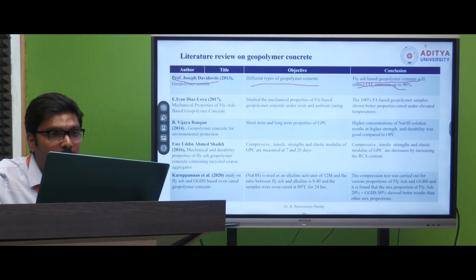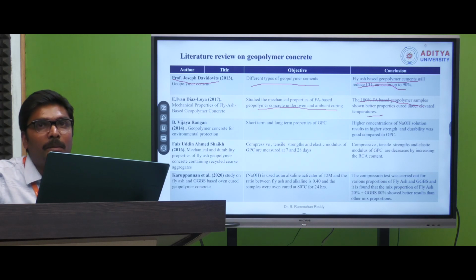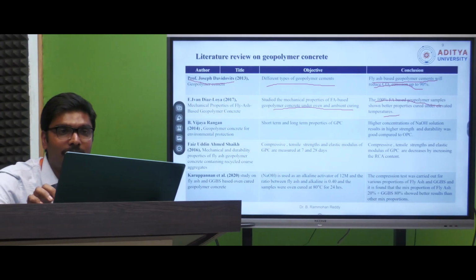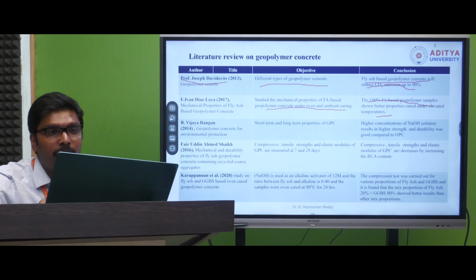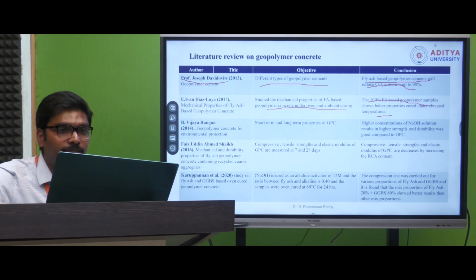And in another study on mechanical properties of fly ash based geopolymer concrete at oven and ambient curing, he concluded that 100% fly ash based geopolymer samples showed better properties under elevated temperature. Most of the researchers present that 100% fly ash based geopolymer concrete will give better results at an elevated temperature of 40 to 80 degrees centigrade.